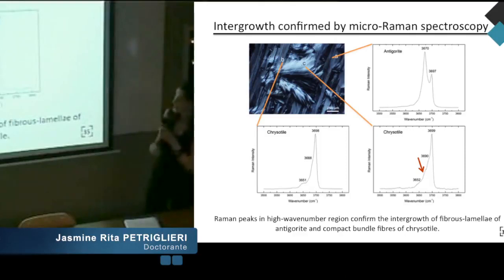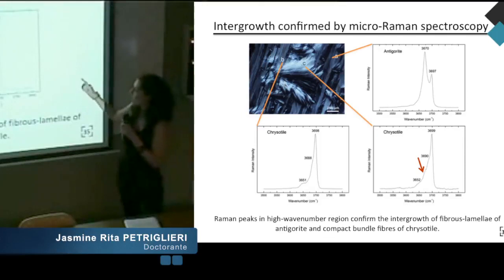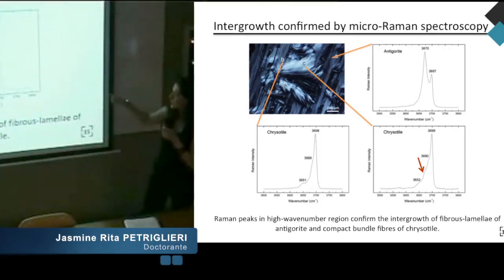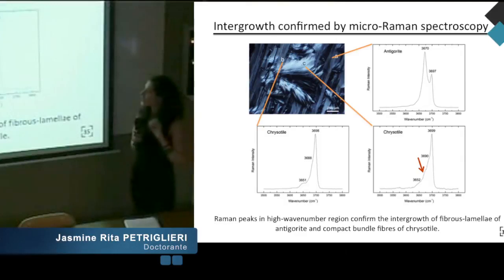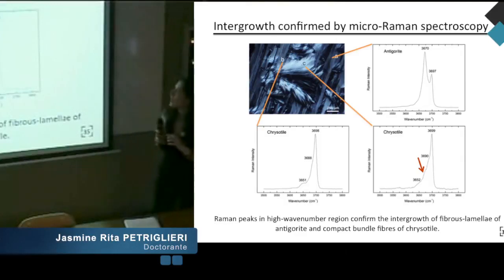And the flexible tuft was confirmed as chrysotile, but it's interesting to notice that a little shoulder indicated by the arrow, which is at the peak position of antigorite, is related to the thickness of the bundles of chrysotile. Compared to the thickness of the tuft in the preparation of samples, the laser beam directly on chrysotile penetrates and is impacted by the presence of antigorite below.